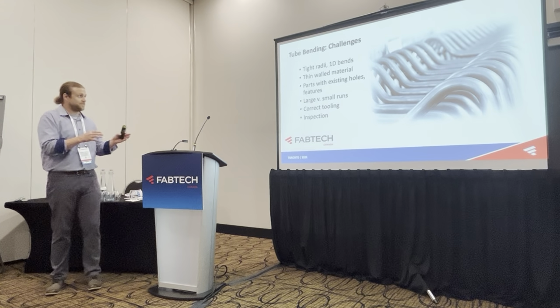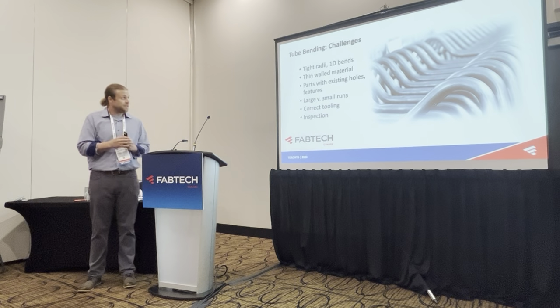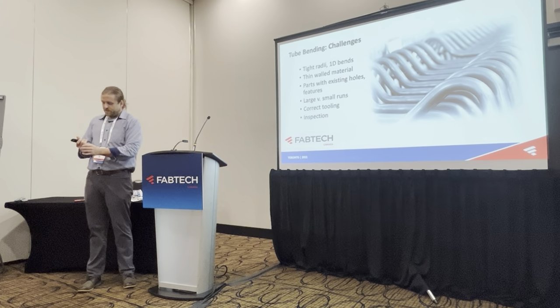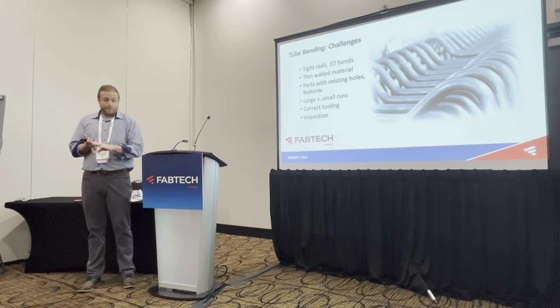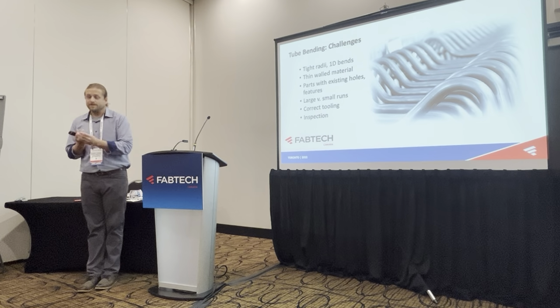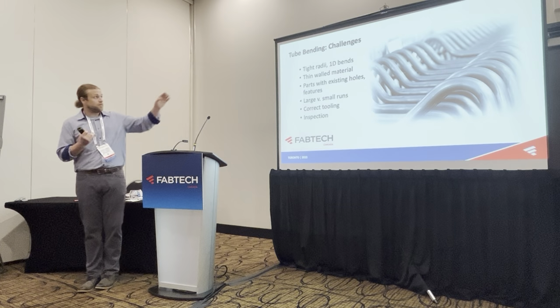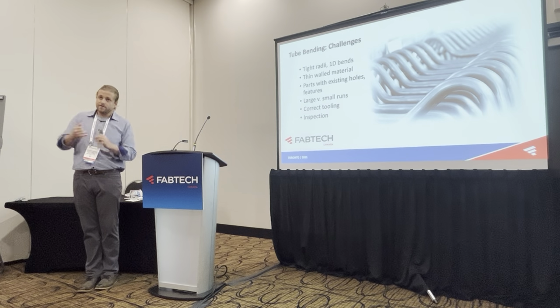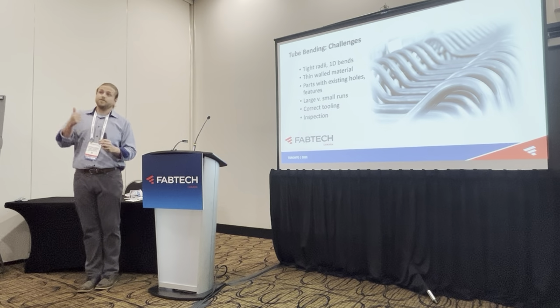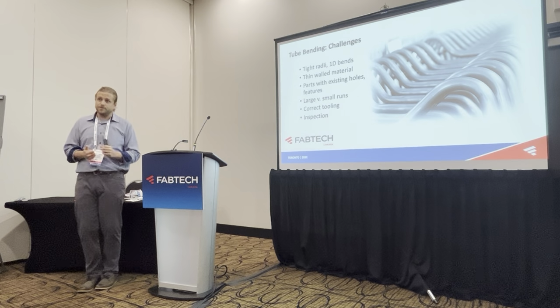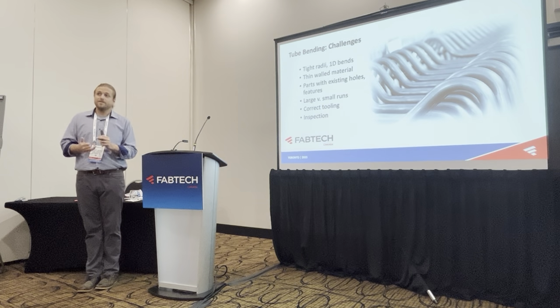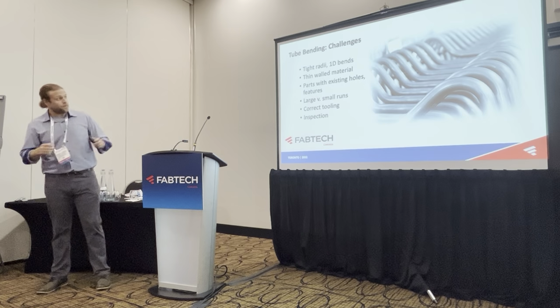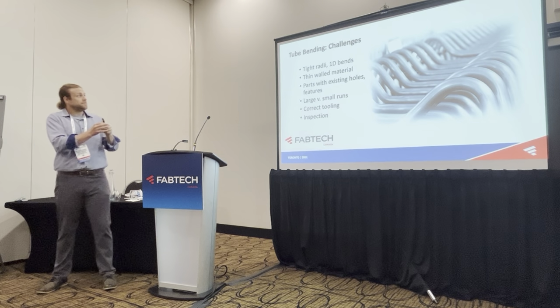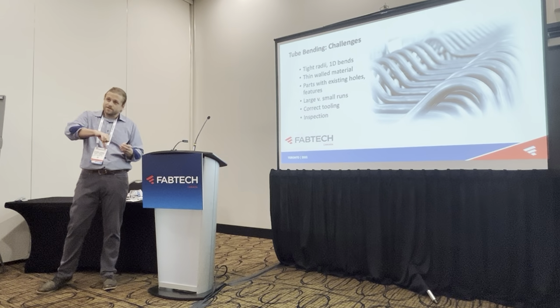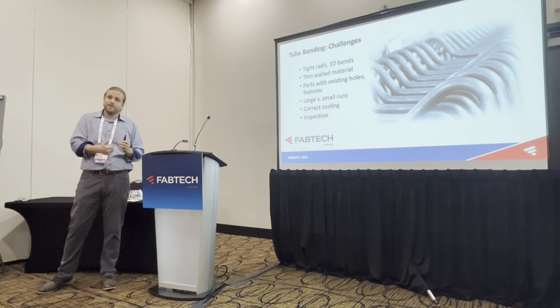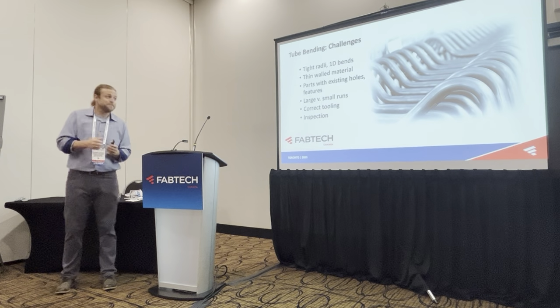So this is where it gets a little bit different. You have your difficulty of bend and your wall factor. Those are two things that you're going to look at. As your degree of bend, 1D, goes down, the difficulty of the bend increases. As your wall factor goes up in value, it increases the difficulty of the bend. So they're opposite of each other. As your radius goes lower, it becomes difficult, and as your wall factor goes up, it becomes difficult.